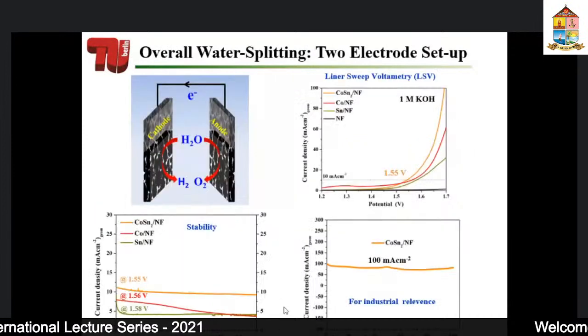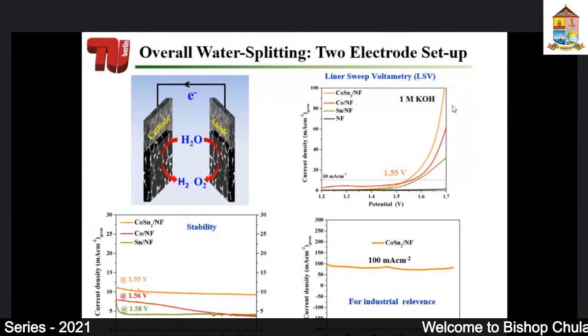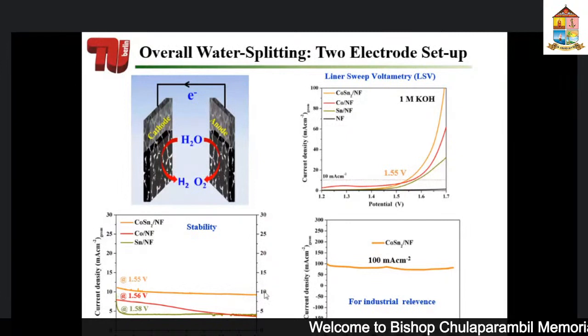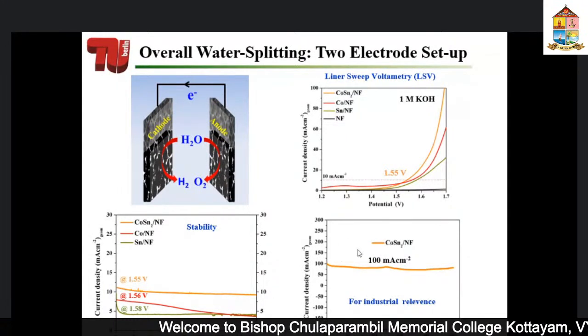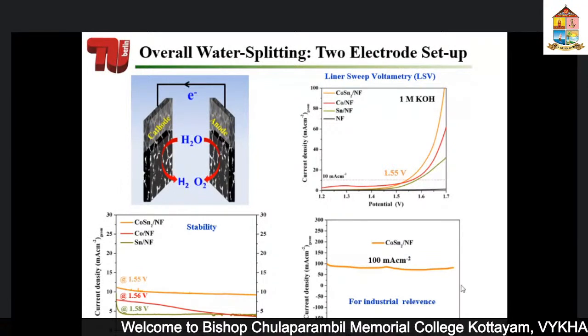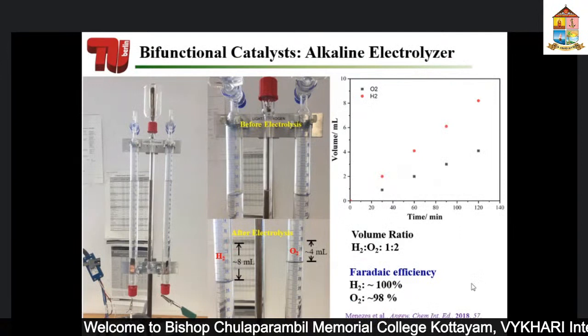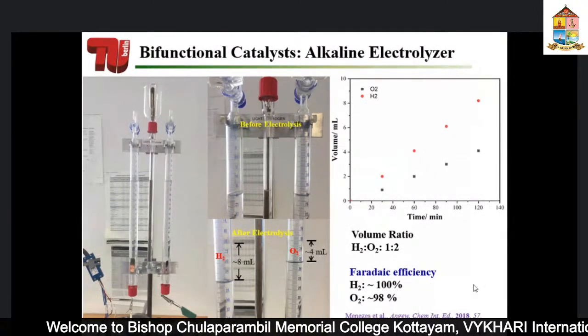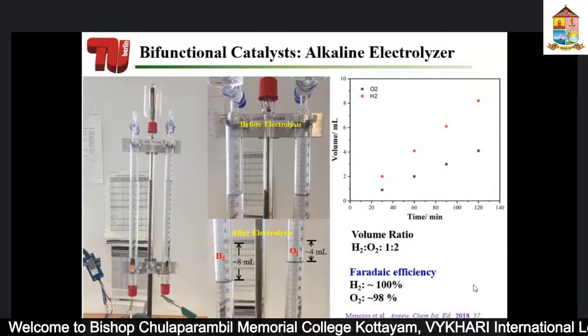Okay, we were interested to make, of course, an alkaline electrolyzer with this. So this is the schematic diagram of how they are constructed, and this is the potential that we show, which is very good. And the stability is, of course, very nice. As you could see, this is at 10 milliamp per centimeter square, which is a standard process to determine the efficiency, 10% solar to fuel efficiency, which is used for solar cells. And we have also conducted this experiment at even higher current densities for over 4 days, and they are quite stable.